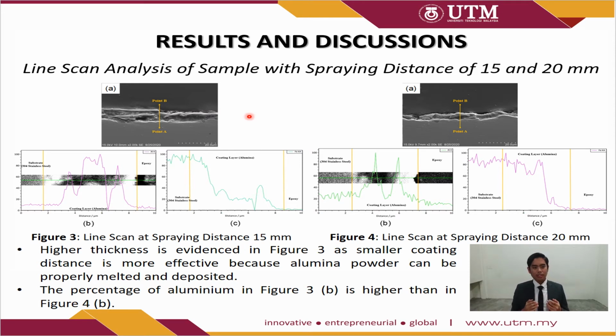In this section, we will be discussing the line scan analysis of the sample with spraying distance of 15 and 20 mm. First of all, figure 3 shows the line scan at spraying distance of 15 mm, while figure 4 represents the line scan at spraying distance of 20 mm. Basically, the coating thickness can be determined based on the sharp increase of aluminium line intensity as observed in figure 3B and 4B. Meanwhile, the coating substrate interfacial boundary is represented by iron line intensity as shown in figure 3C and figure 4C.